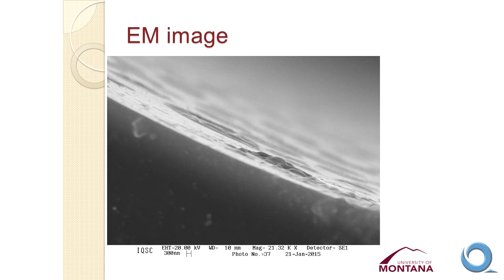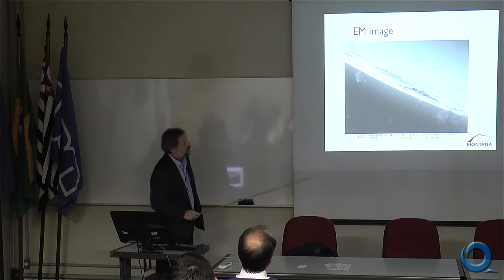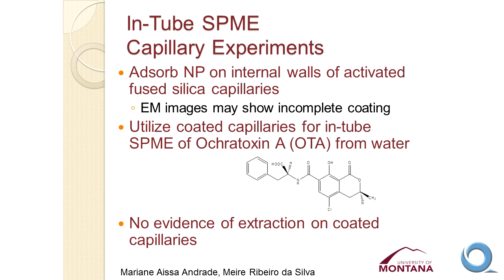And so if we convince ourselves that these are the nanoparticles, what looks like is happening is the nanoparticles are adsorbing to the surface and collapsing and forming a very thin, flat disc on the surface, and that there's a great deal of unmodified silica in between the nanoparticles. So we're not getting a complete coating of the surface, if this image can be believed. What we're getting is a lot of different small discs immobilized on the surface. All right, we tried to use this for the extraction of ochratoxin A. We'll come back to this compound later.